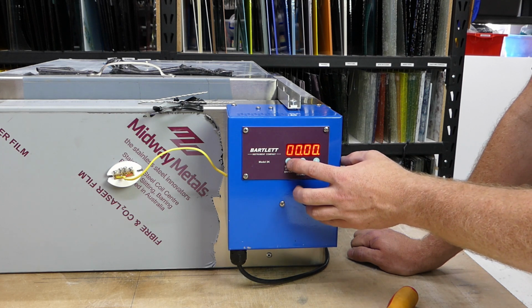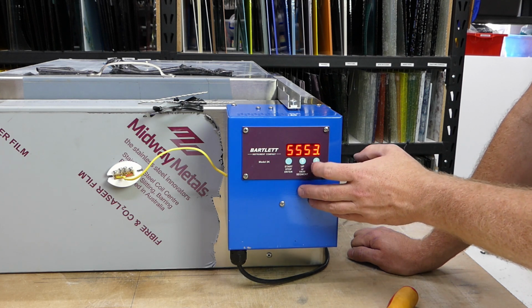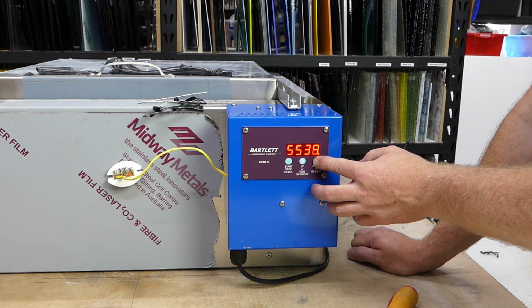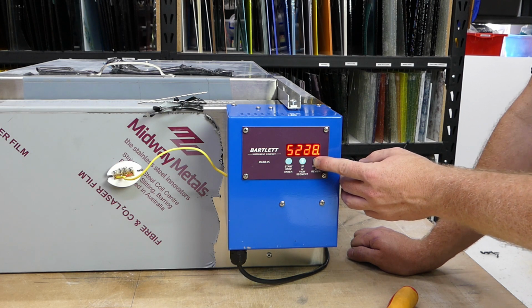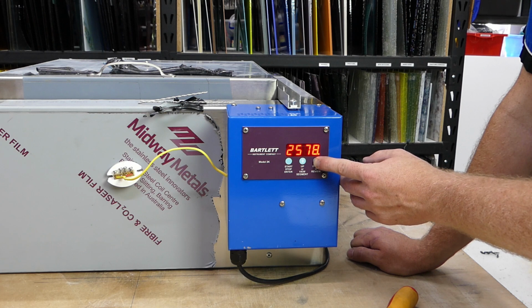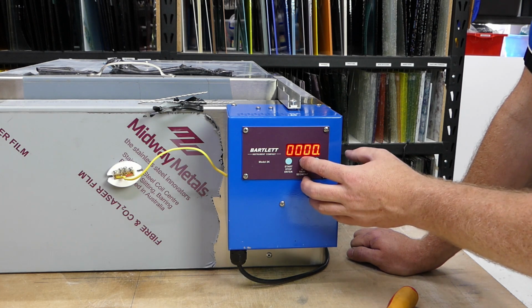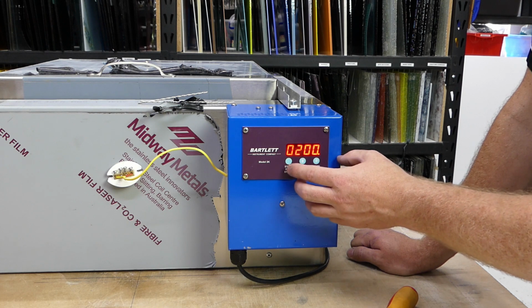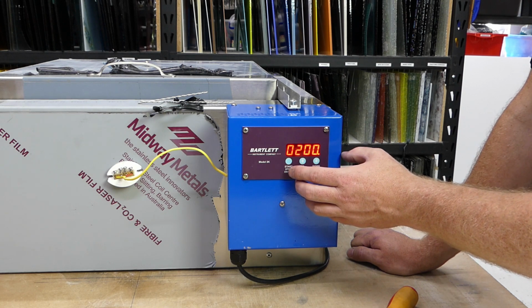And we don't need to hold on that one. And then we just want to ramp down 200 degrees an hour until it's 100 degrees Celsius inside the kiln, and then we're going to get it to turn off. That will be a ramp that is good for all full thickness and full fusing projects inside this kiln for System 96.